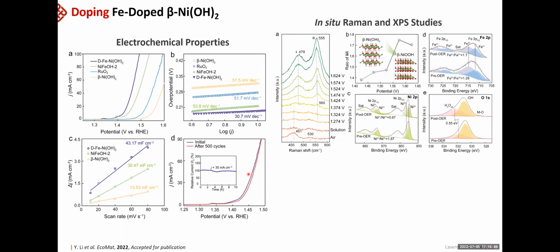We also used in situ Raman spectroscopy to understand what is actually going on. And we see this nickel oxyhydroxide species. We didn't actually look for the iron oxyhydroxide species because we believe that is still too little, and actually we couldn't identify it from this peak. Maybe the nickel oxyhydroxide peak is too dominating. But anyhow, we saw that at quite an early stage, at around 1.37 volt, we start to see the formation of nickel 3+ species. And also from the XPS, we can compare the before and post species.